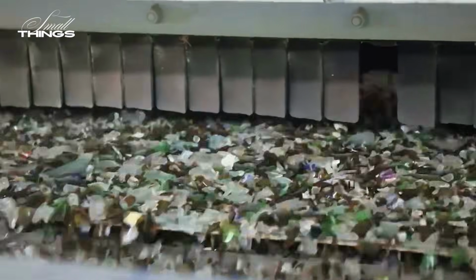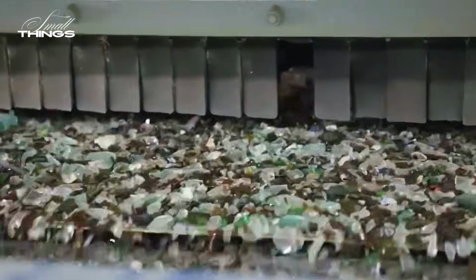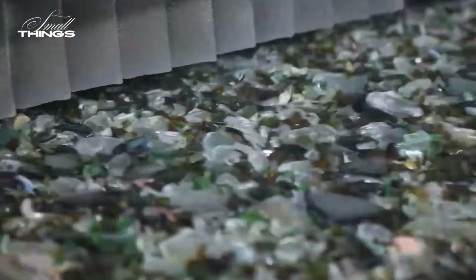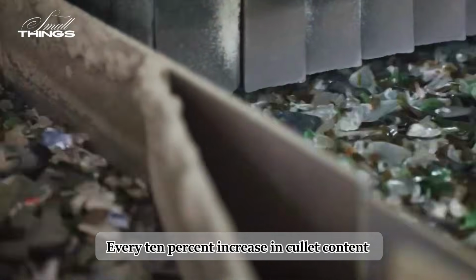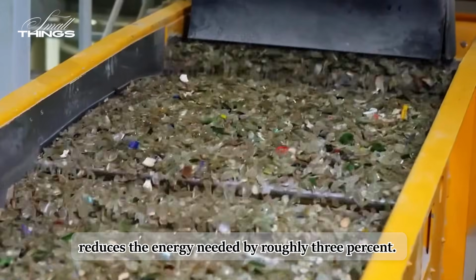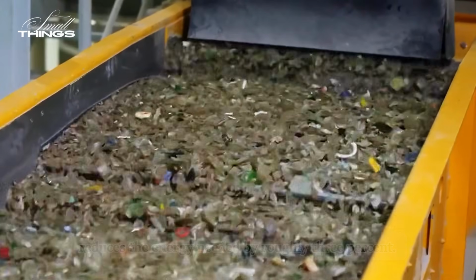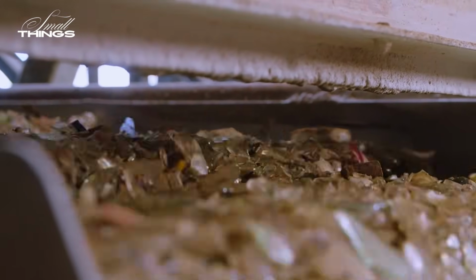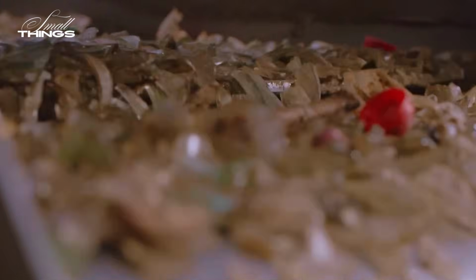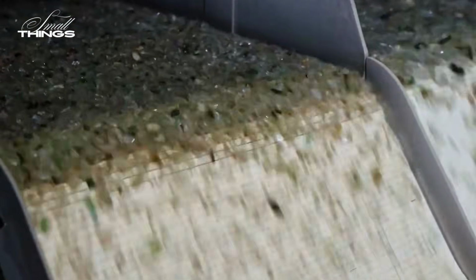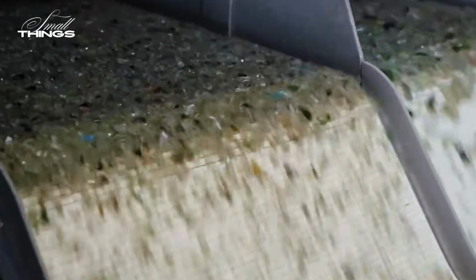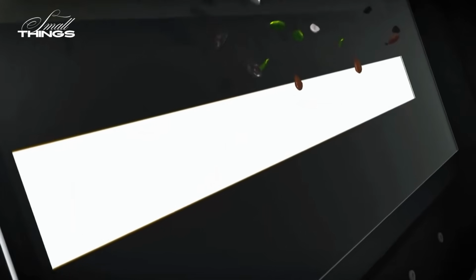Cullet has a lower melting temperature than raw materials, which means it costs less energy to process. Every 10% increase in cullet content reduces the energy needed by roughly 3%. The economics of recycling and the physics of glass point in the same direction. After crushing, the cullet cascades through an optical sorting system. Laser sensors scan every fragment in real time, identifying color and composition.